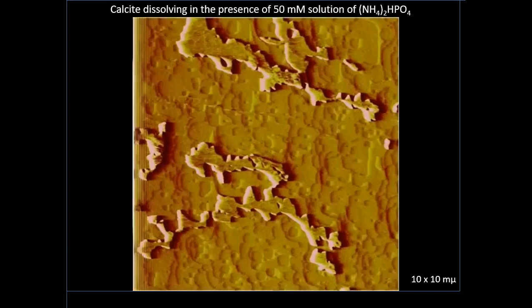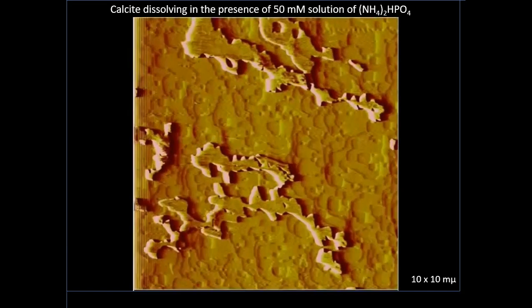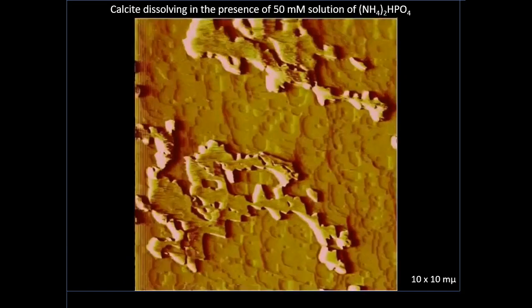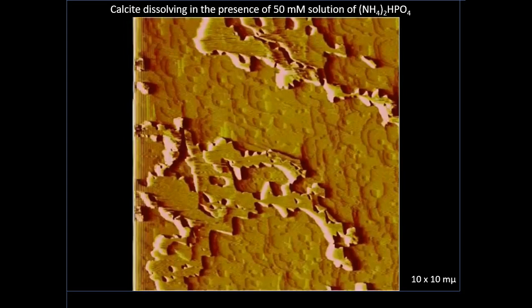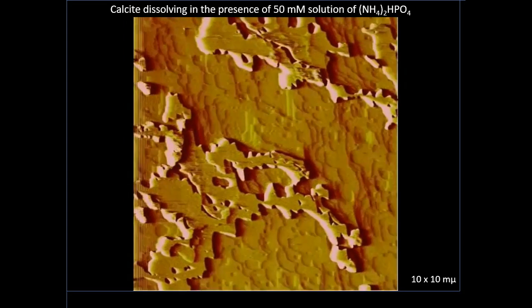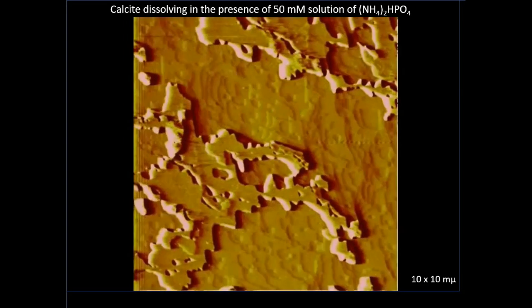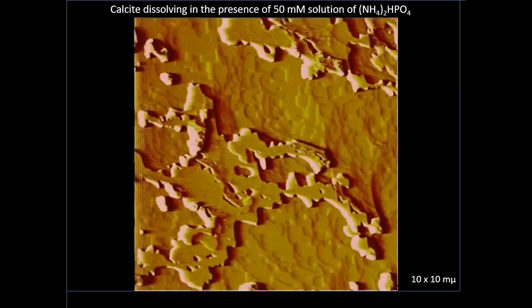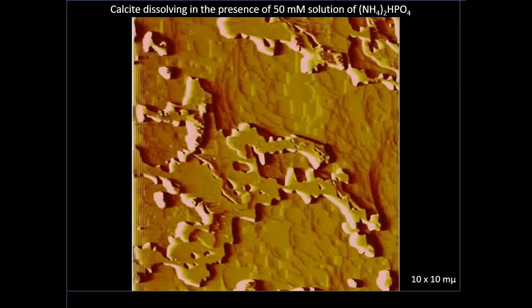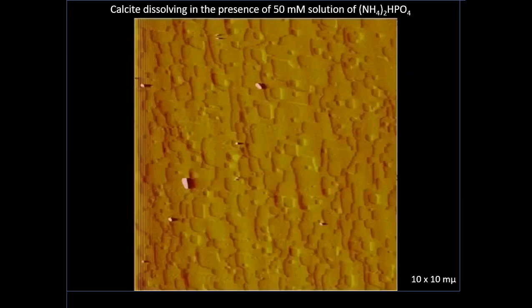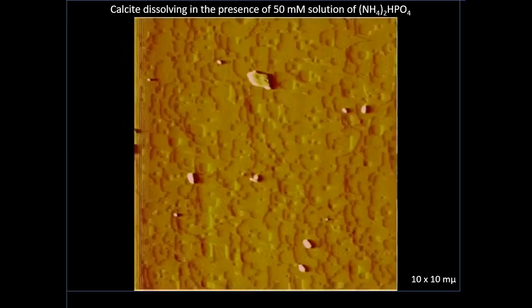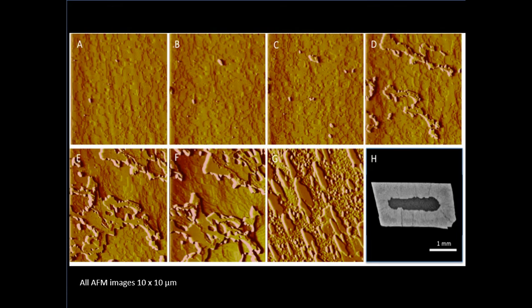And once we've got one nanoparticle, we get more in the merging together with other nanoparticles. Sometimes they form and dissolve. Sometimes they do this and end up covering the whole surface, and we have the formation of a new phase. I've stopped this film as well so that we can see A, B, C, the progression. This is happening within about 2 hours.